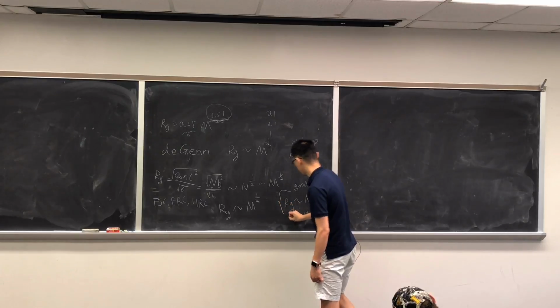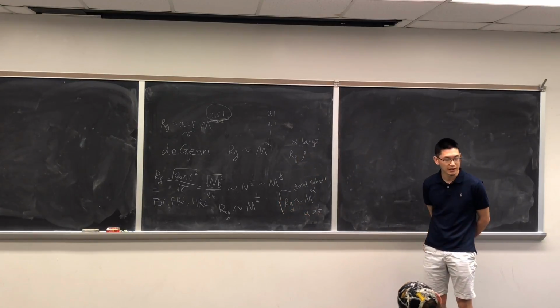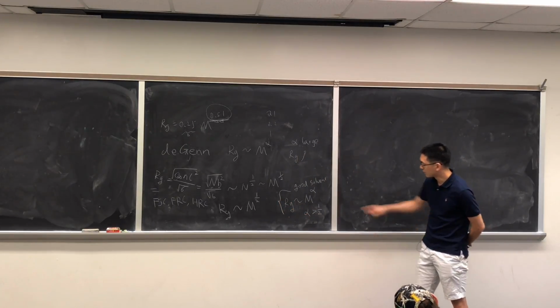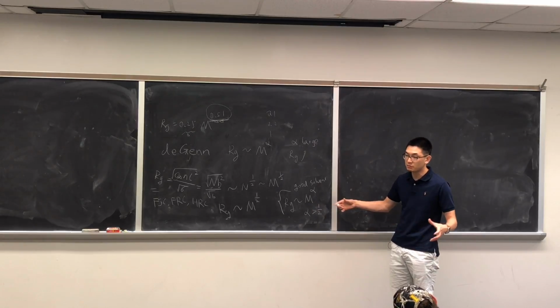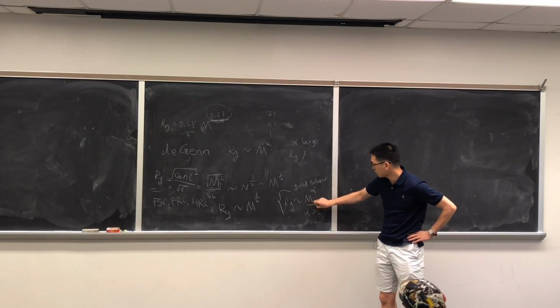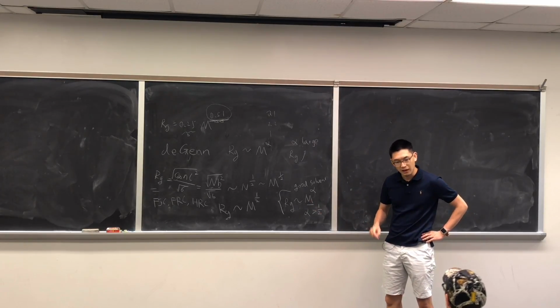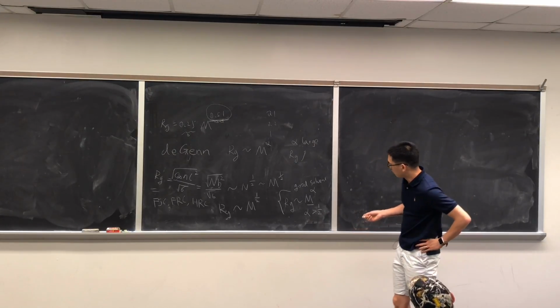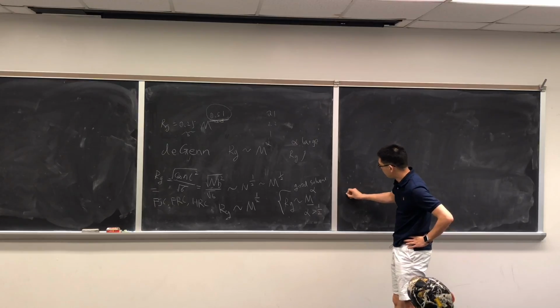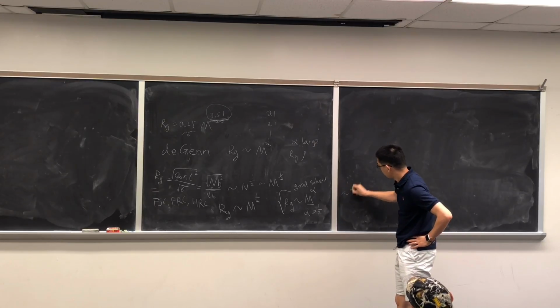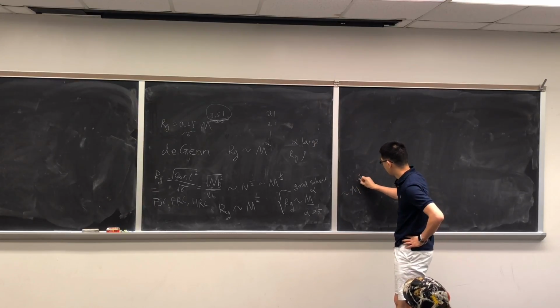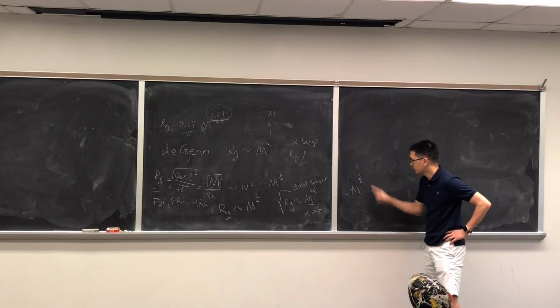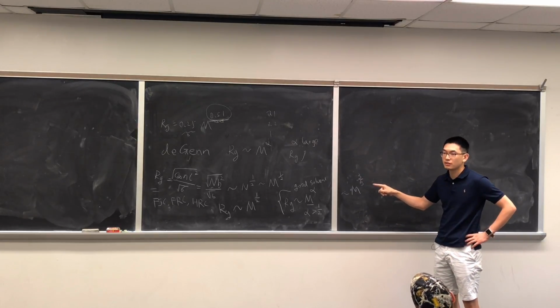So that's the case if it's a good solvent: you can see it has a much stronger dependence on M. We won't discuss it in more detail, however, we will learn it in the next chapter. It's actually a power of 3/5 for the good solvent.